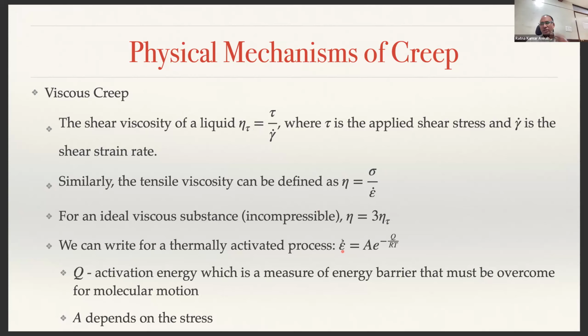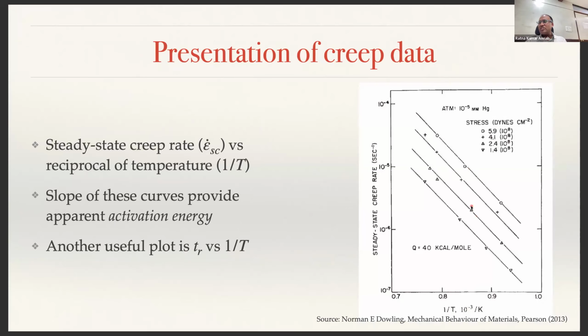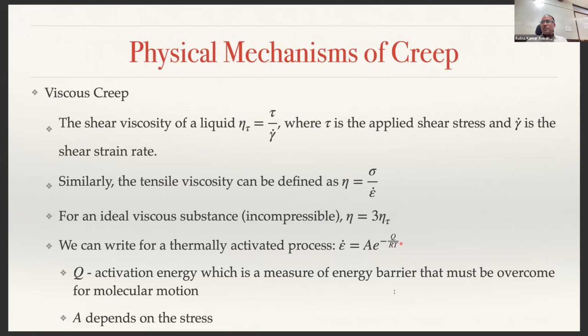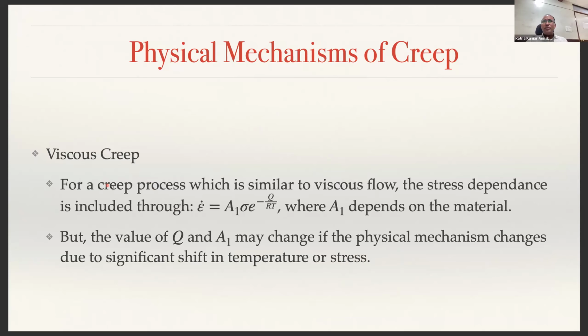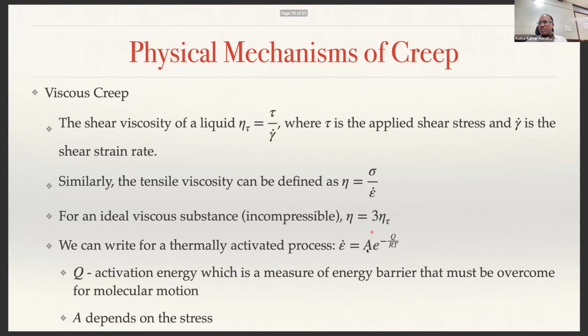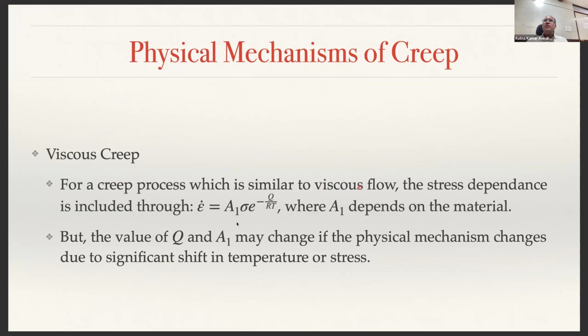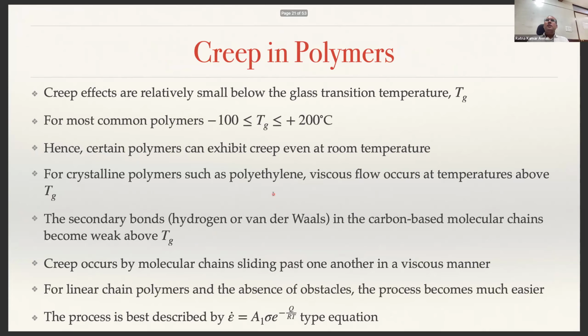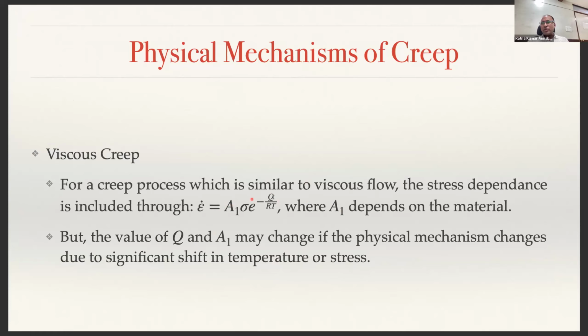Now, the strain rate we are talking about can be represented in this Arrhenius form, where Q is your activation energy, which we have actually measured here for each material. And R is the gas constant, T is the absolute temperature. And A again depends on the stress that you are applying. So the viscous creep can now be represented by, because A is a constant that depends on the stress, we can bring out that stress explicitly, and we can write epsilon dot is equal to A1, which is a material dependent constant, times stress, e power minus Q by RT, where Q and A1 are material constants. They will change depending upon whatever creep mechanism is at play. So typically you will have different A1 and Q for a given material, depending upon the creep mechanism that is at play.